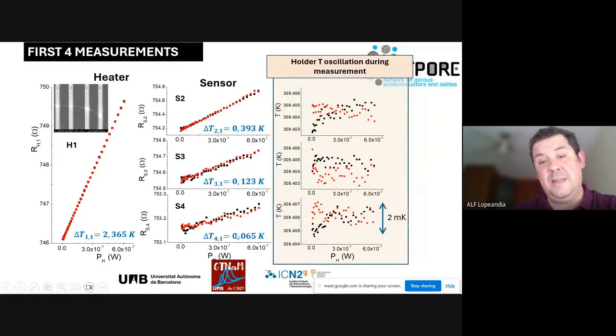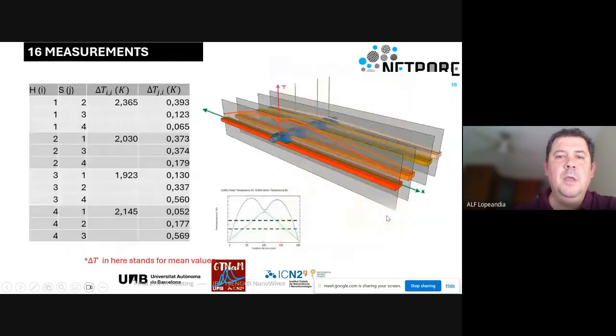That's the reason, in fact, that the small movement of the last wire is why we need such good thermal stability of the temperature bath. This is the stability of the temperature bath, and these are 2 consecutive measurements, one in red and the other in black. This is the stability that we got during the measurement, in all cases well below or around 2 millikelvin.